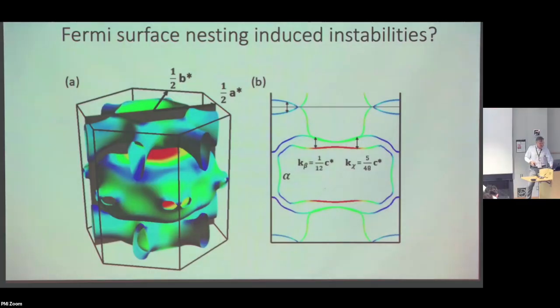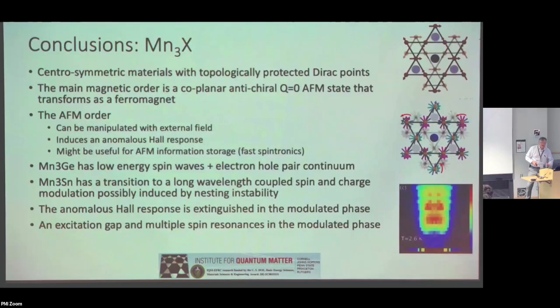Well, so I think with that, I should probably come to a close. I have a few words I was going to say about this little friend, which is, we've looked at the magnetic orders using polarized neutrons, and we've analyzed the spin wave excitations. Those are heavily damped at high energies, which is what you expect when you're dealing with magnetism that's carried by the same bands that are also conducting charge. And so there's always a lot of excitations possible that lead to damping.